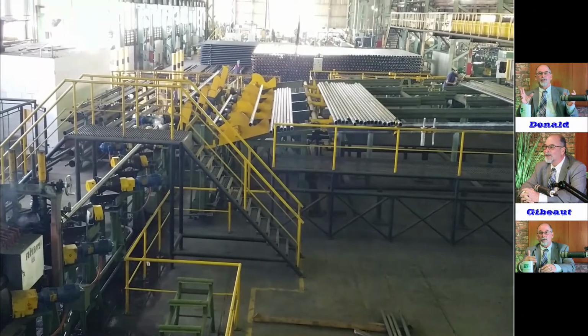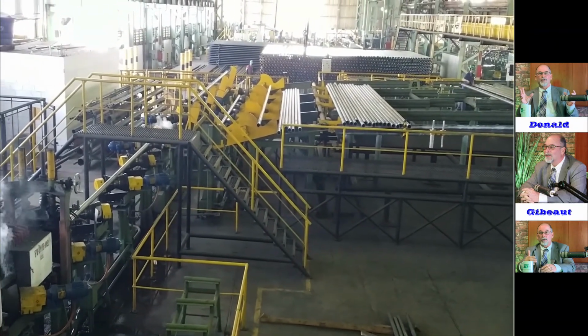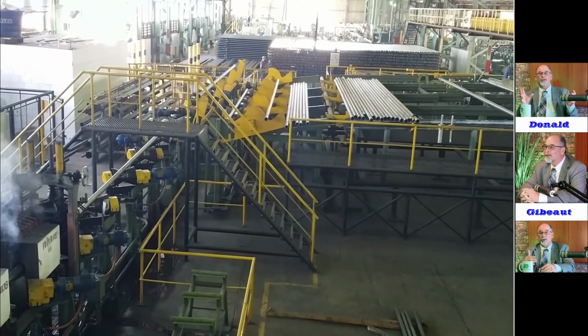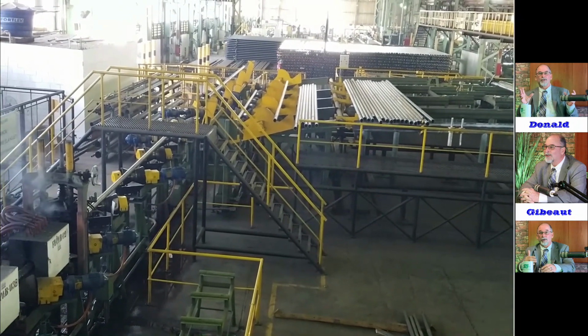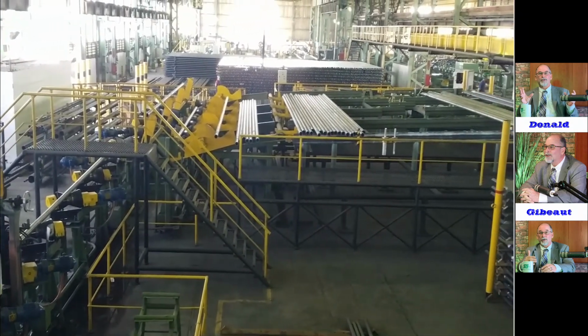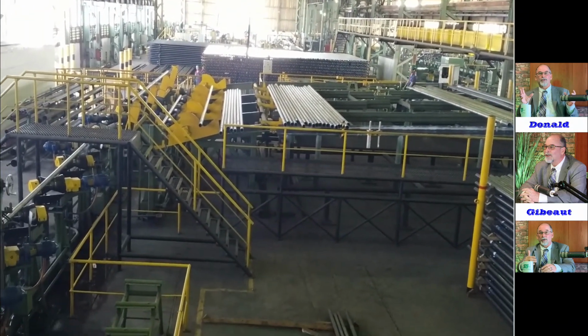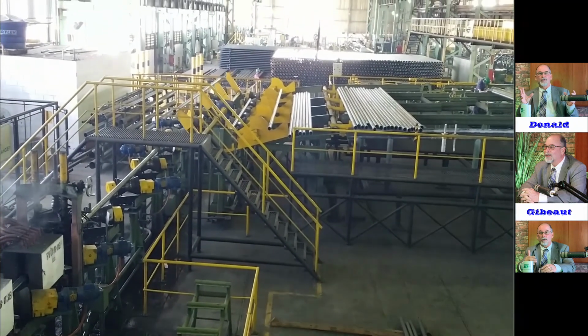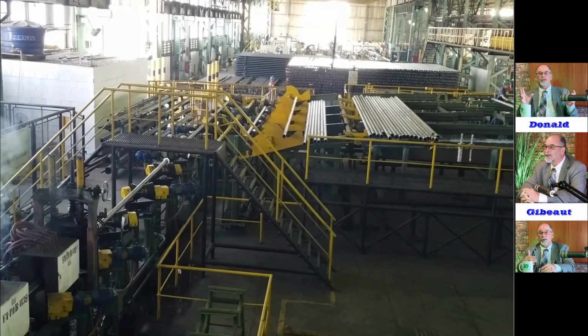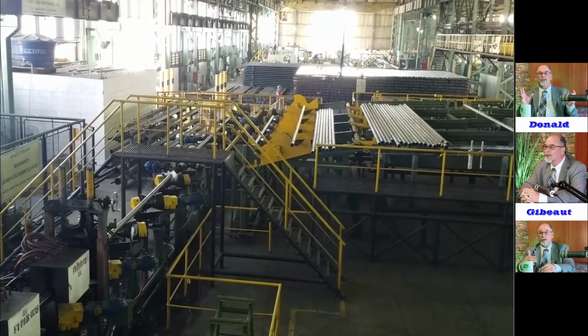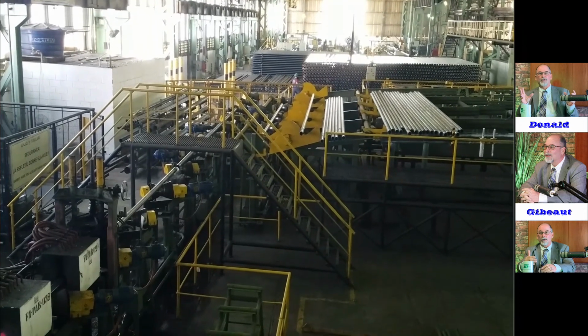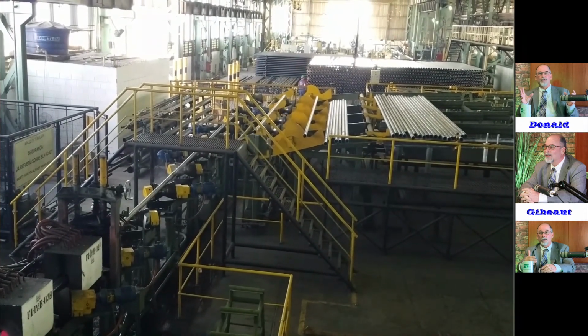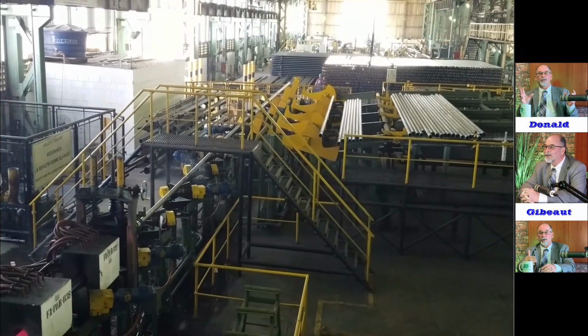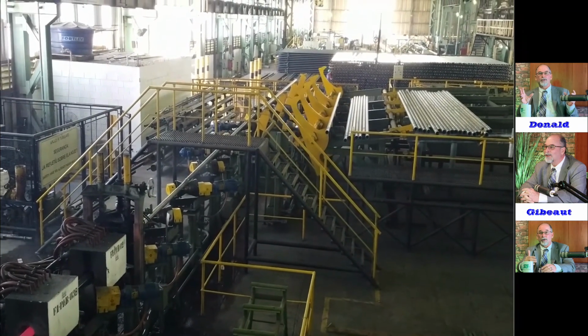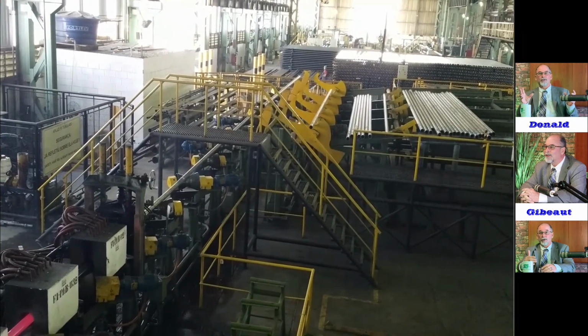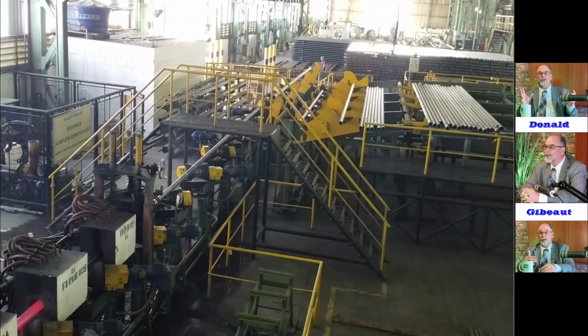This is the end feed table. Bring the pipe in. You can see the stop on the back, just to slow down that inertia. The pipe's going forward, and you keep a buffer in the front of the line so you don't ever build in a gap. Now you'll see that this is a rotary transfer, not a paddle system. On our higher tonnage lines, we use the rotary transfers. That's out of the way quicker. But you saw that pipe race up and touch that pipe going before it gets into the austenitized section. One is always queued up. And these rotary transfers are a lot more expensive than the paddles, but they're critical on the higher tonnage.